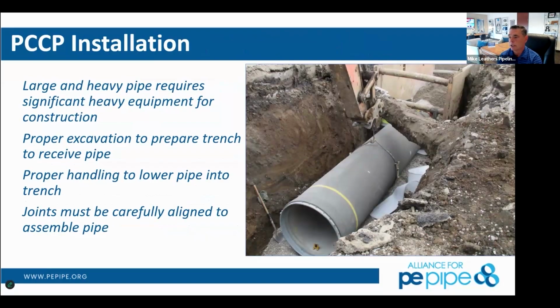So as an owner, engineer, and contractor, it's important to understand the installation requirements and all the risks. PCCP is a big, heavy pipe. If bedding or backfill wasn't or isn't being designed and inspected and required on the job site, settlement can occur. That may open up the joint and allow leaks over time that can cause some of these failures. So if gaskets weren't properly placed and tested, if they're pinched or rolled or have corroded, they will leak and it will cause corrosion over time. If these gaskets are placed correctly and the joints weren't welded or grouted correctly, that can also cause failure. Even handling from transport to install, the linings and mortars can be damaged. So it's very difficult to make a pipe that's contractor proof. Big heavy pipe can be an advantage, but it can also be a challenge. Next.